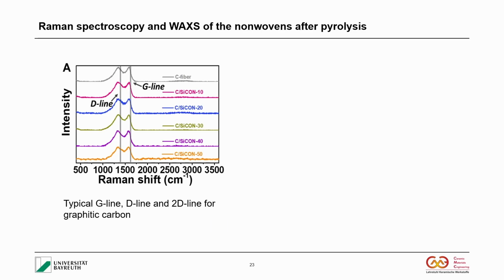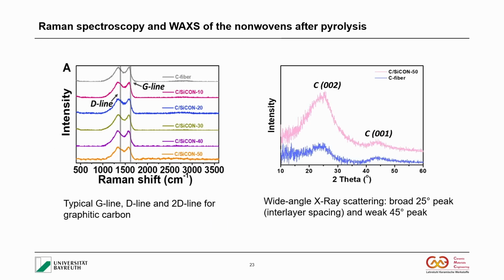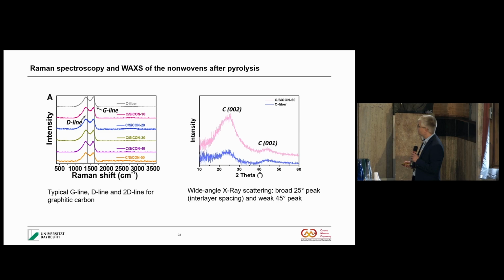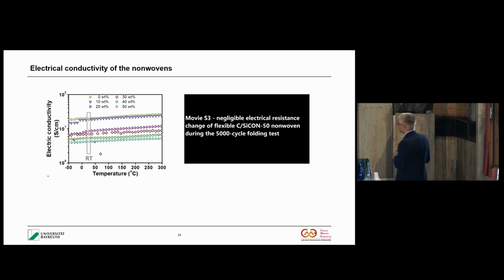And then what is also important, looking at the microstructure, or let's say the structure of the fibers. So here, if you use Raman spectroscopy, you have the typical so-called G line, and also the D line for the amorphous carbon. And you see here you have the pure carbon fiber, and here you have the hybrid fibers, and you still see this D line and the G line. So that means the amorphous carbon was still present. Even if you use WAXS, you come to the same conclusion. So that means you have amorphous carbon inside.